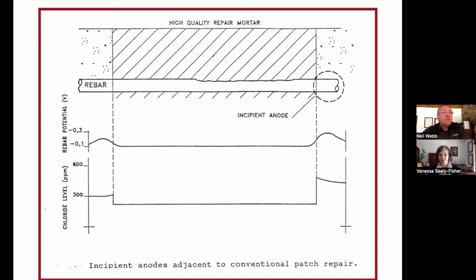So if we look at this particular situation, there's now a conventional repair. The corrosion of the rebar was not too bad. So we chopped out the concrete, put in a nice high quality concrete patch, and yeah, we've just moved the problem. We've just moved the problem to the edge of the patch. And those of you who have been involved in conventional concrete repairs may well have experienced this, that you go in, repair a patch, and 2 years later, it cracks again next to the patch. And you just carry on and carry on.